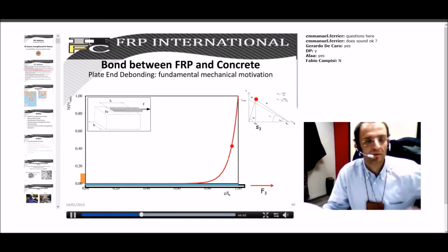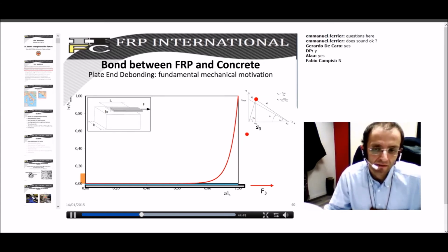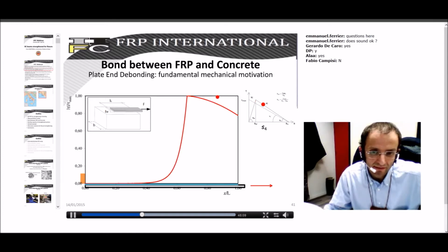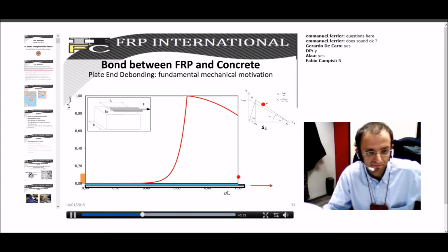an exponential distribution, and then this is the maximum value of S3 corresponding to an exponential distribution. Because once you attain S3, any increment of S3 will stress the interface in the nonlinear range. So you will have another distribution of this part. So you will have here the S elastic limit, and this part will be stressed in this. So from here to your left, you have displacement which are smaller than S elastic. From here to your right, you have displacement which are up to S4. Here we have S4. And then in this point, the maximum tau is smaller than the tau you attain in this point, which is the maximum one.